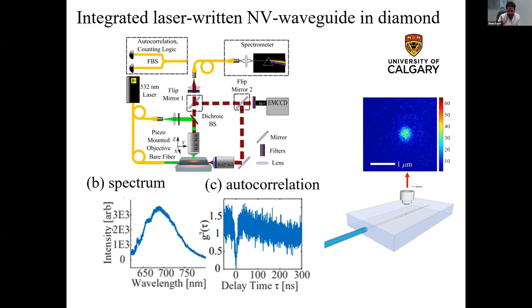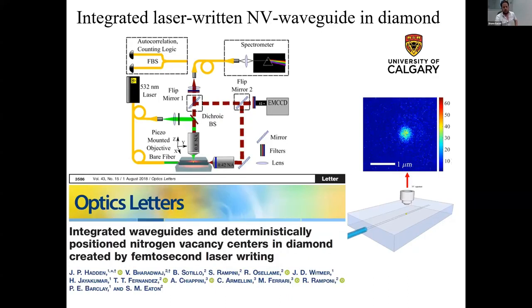Now that we have these building blocks to form both photonics and NV centers with the laser, we thought about combining the two. So entirely made with the laser in the very same process step, we formed first this waveguide, and then we formed this static exposure in the middle of the waveguide, which we then annealed the entire sample. And thankfully, the waveguide properties were not degraded after this 1,000 degree thermal annealing. But in fact, we were able to form this single NV in the static exposure in the middle of the waveguide, this single quantum bit. And so we showed the first ever coupled NV waveguide formed entirely with the laser. And that was done in collaboration with the University of Calgary.